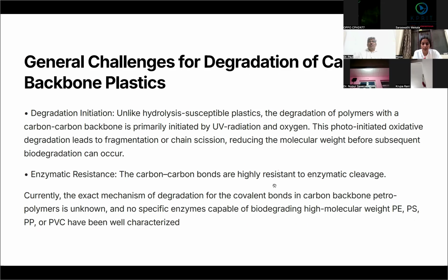So, what are the general challenges for degradation of the carbon backbone plastics? Unlike hydrolysis susceptible plastics, such as the biodegradable plastics, the degradation of polymers with a carbon-carbon backbone is primarily initiated by UV radiation and oxygen. This photo-initiated oxidative degradation leads to fragmentation or chain scission, reducing the molecular weight before subsequent biodegradation can occur. The carbon-carbon bonds are highly resistant to enzymatic cleavage. Currently, the mechanism for degradation of the covalent bonds of the carbon backbone in the petropolymers is very little known.